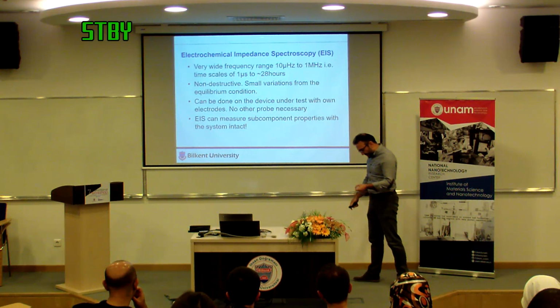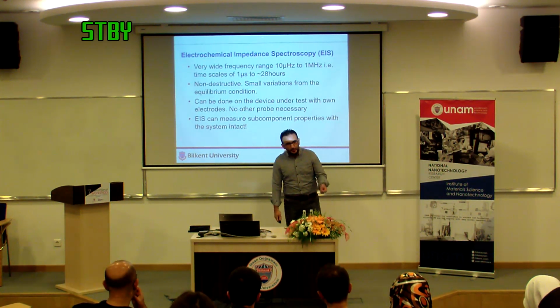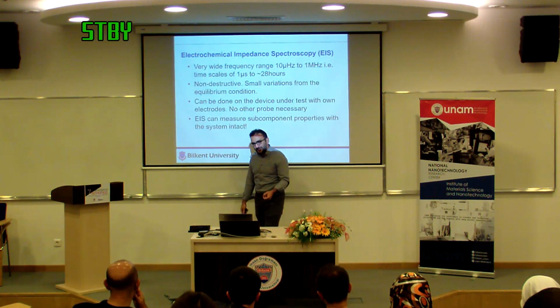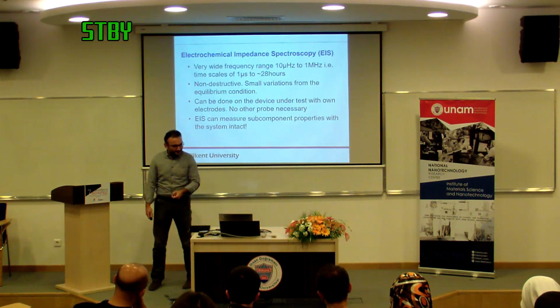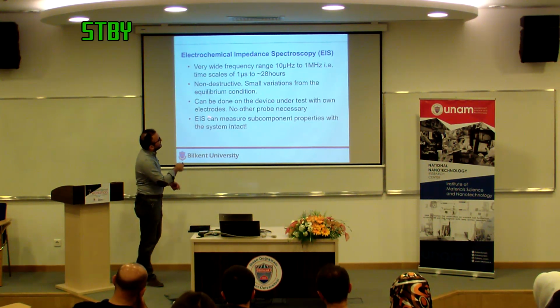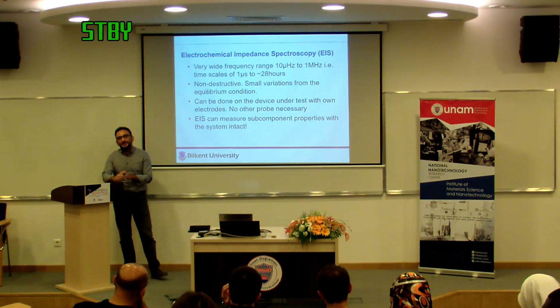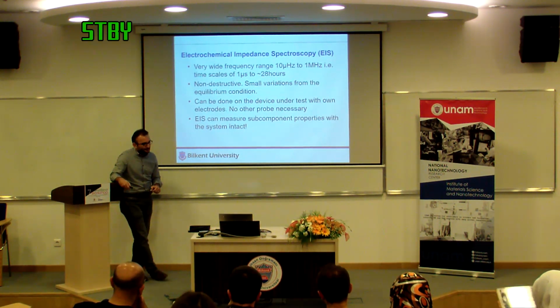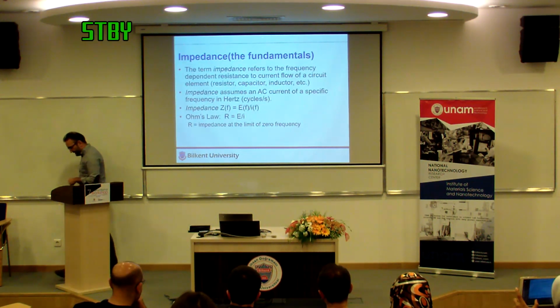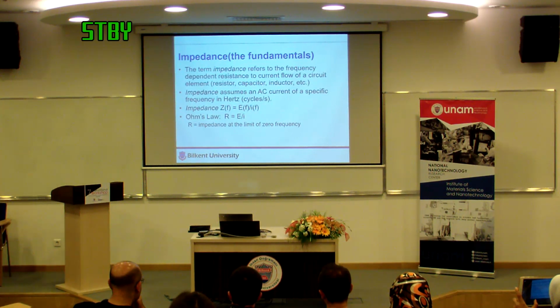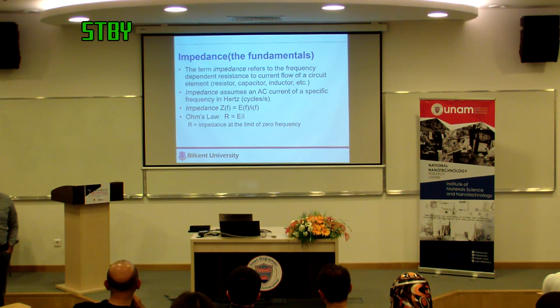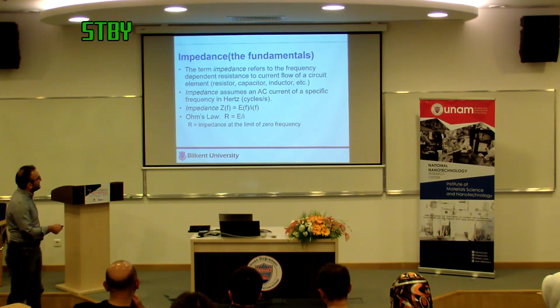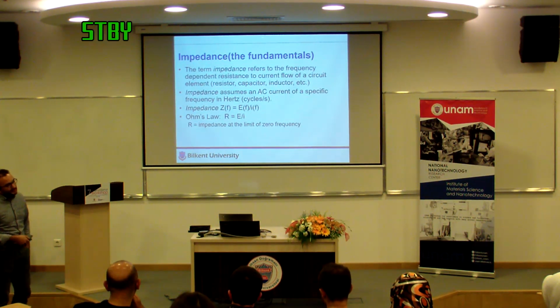Which is important because a lot of these energy storage and conversion devices do have events going on in the microsecond and millisecond time scale in addition to the day time scale. Its power lies in this bullet number 3: it can be done on the device under test without any additional probes. The way it's done is it's a measure of impedance, which is essentially a resistance measured in AC, and it follows simple Ohm's law. V over I equals Z. This is not different than Ohm's law, it's just generalized to sine waves as opposed to DC levels. You can think of Ohm's law as the impedance limit at zero frequency.